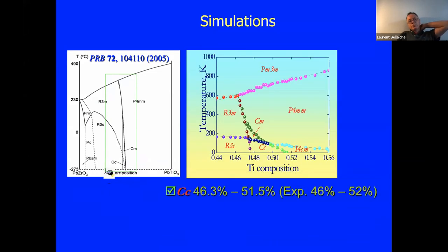And what do we confirm? First, we confirm that there is indeed a CC phase, and what we found is for a small, narrow range of composition, extremely close to the experimental one. We also found other things. We found that there is this I4CM phase. It's a tetragonal phase, but in addition to polarization, it has a tilt about the z-axis. And later on, when understood, this was confirmed experimentally.